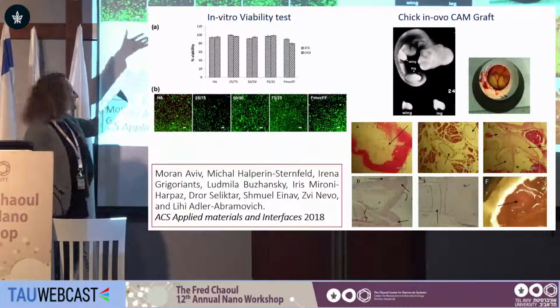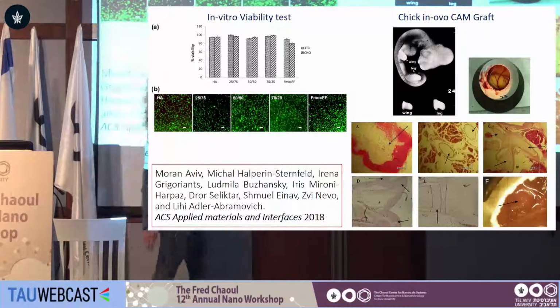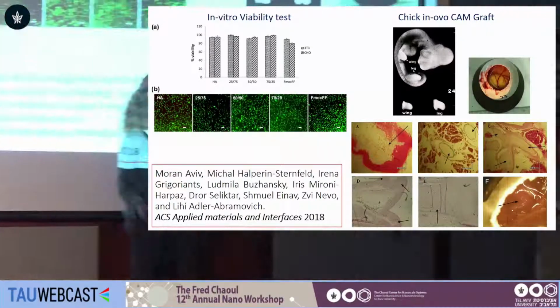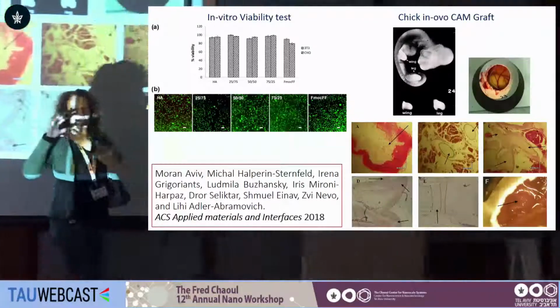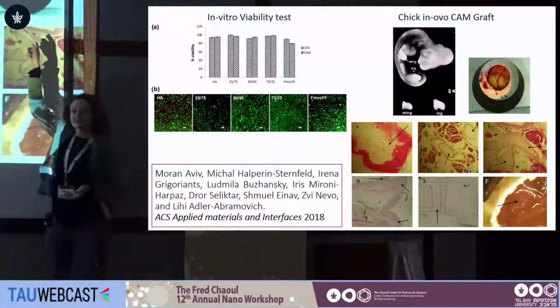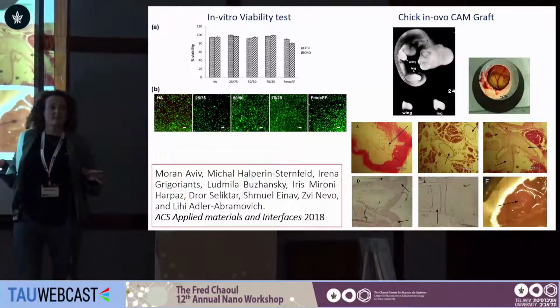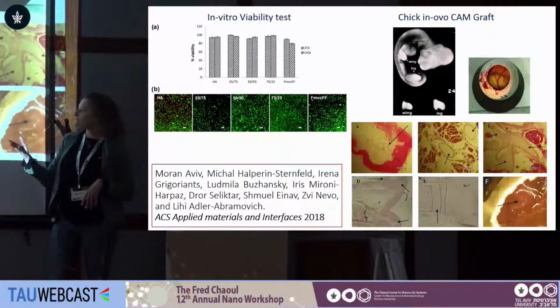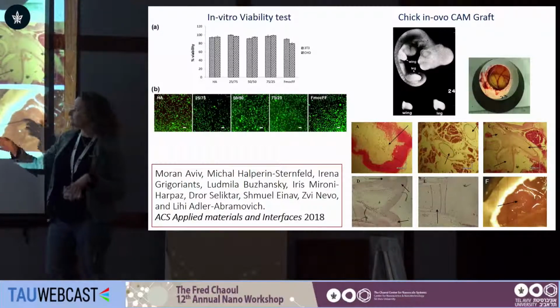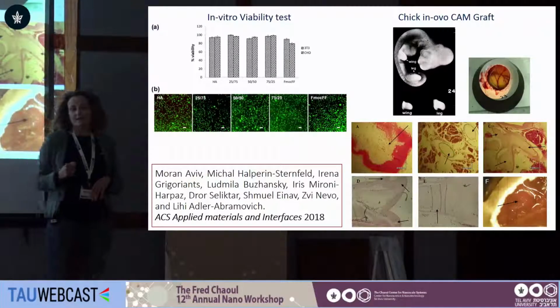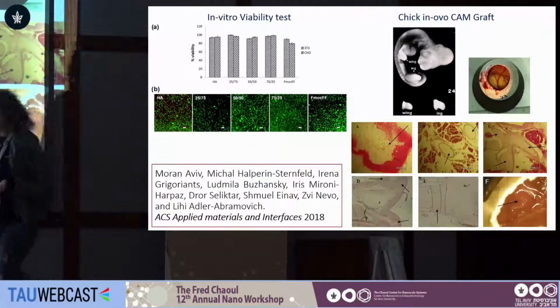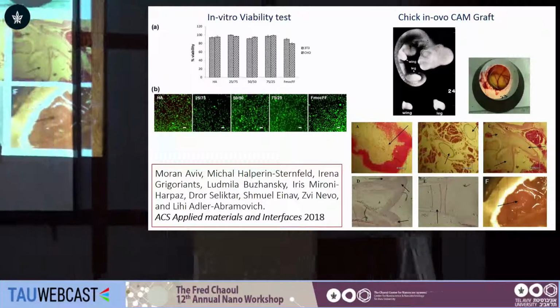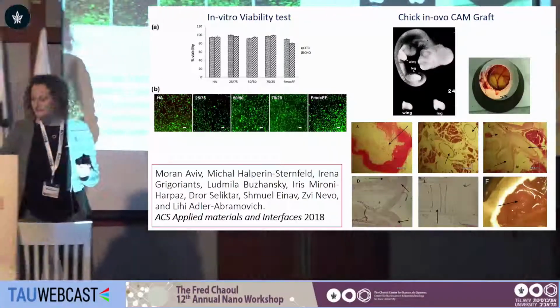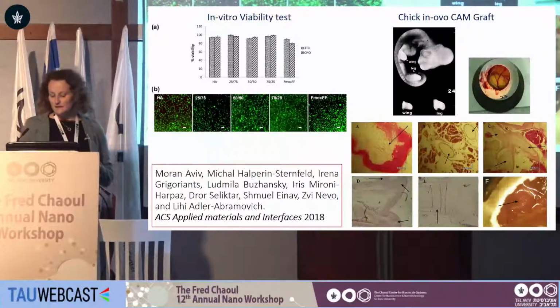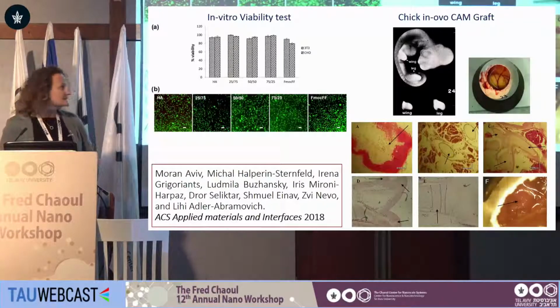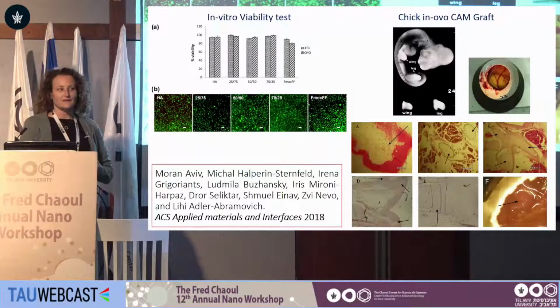And another interesting experiment that we did, we harvested limb buds from a chick embryo, embedded them in our hydrogels, and placed them together on the upper membrane of a fertilized egg. The results were amazing. I'm not sure if you see it clearly, but the limb buds developed into a fully formed leg or wing after 7 days in ovo. So based on our results, which were recently published, we see the great potential of these hydrogels to serve as 3D scaffolds for drug release and tissue engineering applications.